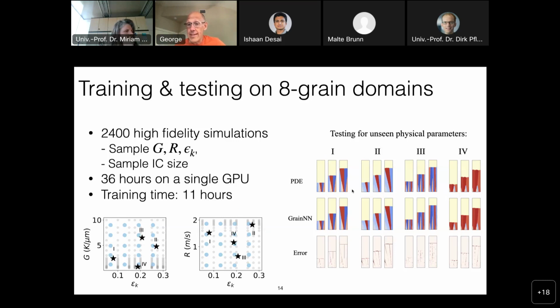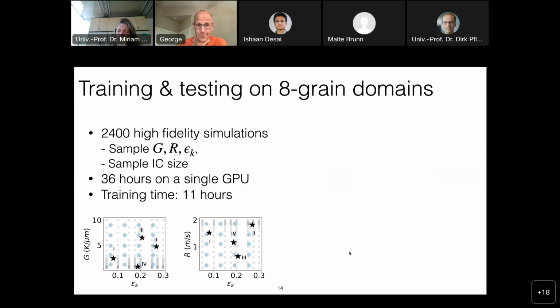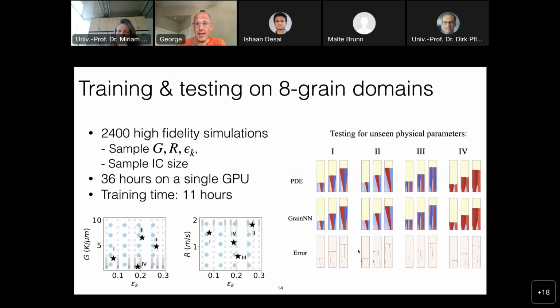And then these are indicative results for some of the blue dots in the testing. So these are again 8-grain testing values. So this is the prediction for the PDE, and this is the simulation that we compute for the grain. So if you can see here, there is a little bit of curvature that we don't model. We just have the excess area, and you can see the errors here. We get about 3 to 5% error. We call this in distribution because we train for 8 grains and we test on 8 grains, but in different parameters.